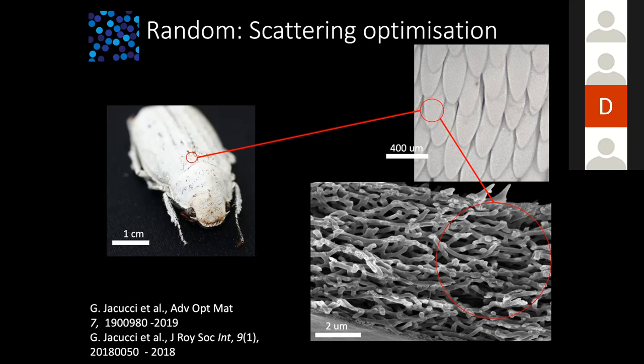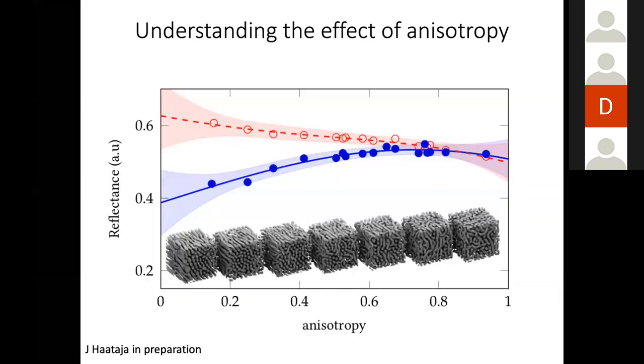But what was really surprising is that in nature, white is not obtained with inorganics, because if you are an insect, you cannot produce titania. Instead it uses a network of chitin and protein, but by optimizing the characteristics of the network, creating this random network structure, these beetles are able to create a perfectly opaque layer in only a few microns. What does it mean? If you compare with a layer of paint, in order to cover a wall you would need at least 150 microns, whereas with only 7 micron thickness this beetle is able to make the same whiteness without the use of any inorganics. So it tells you that these natural structures are pretty well optimized.